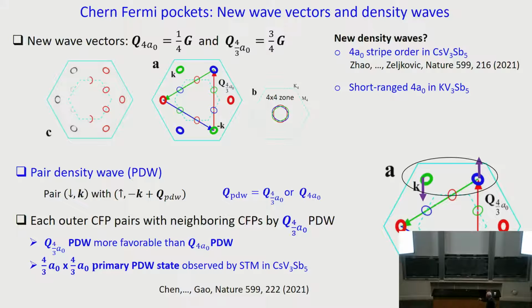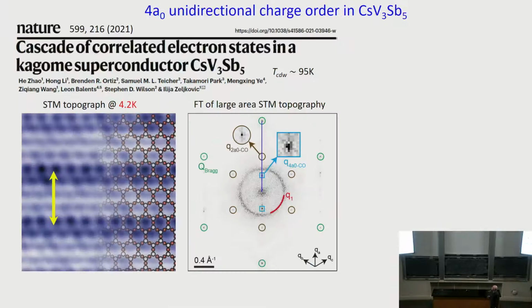And indeed, STM has seen such pair density wave ordering. So I'll show you these experiments quickly. This is in the cesium-based compound, CDW transition temperature 95. They go to 4 Kelvin, and you do a Fourier transform of the topography. These are the Bragg peaks.